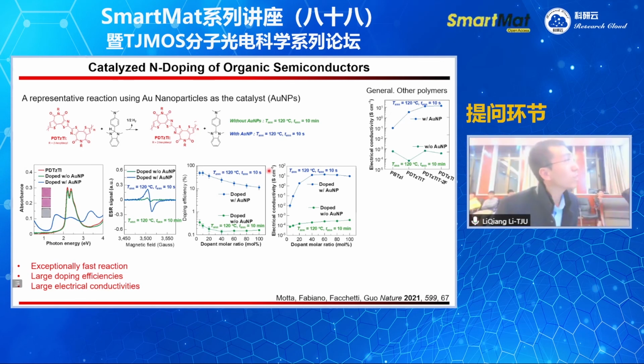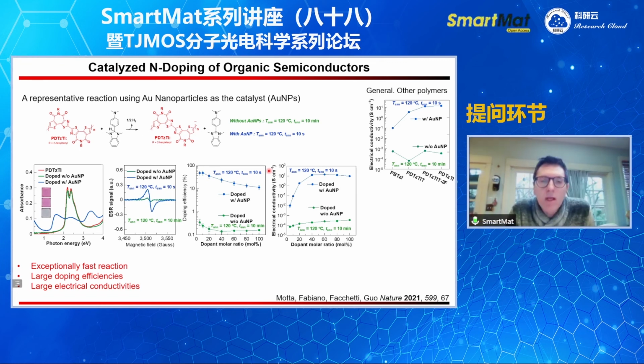Then, is the doping process reversible? I mean, can you dedope, can you reverse the n-type doping process? Yeah, it is reversible. So if you take the color polymer, for example this polymer doped, and you re-expose it to the air, it depends on the polymer and the thickness of the film, but after a certain amount of time you can dedope it.